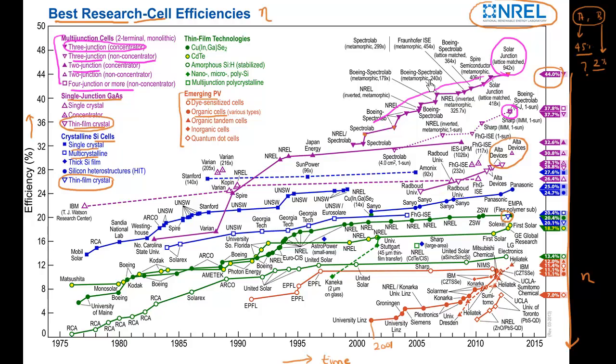Another thing I noticed is that for these multi-junction solar cells, the people report efficiencies for a non-concentrator, that is at a concentration of one sun. And that is, then you achieve efficiencies which are in this range, 37% range. But at the same time, when you apply a concentrator, or you increase the concentration of the sun by concentrating the sunlight, then you get a much higher efficiency. And the higher you go in concentration, the higher the efficiency you get. And this is kind of again represented over here, where you can see that this particular cell had a concentration of 406 suns. And the maximum efficient, the record efficiency holding cell currently, it had a concentration of 942x or 942 suns. And you can go higher than that, but of course, that would heat up your cell. So so far, maximum concentration which holds this record efficiency is around 940x.